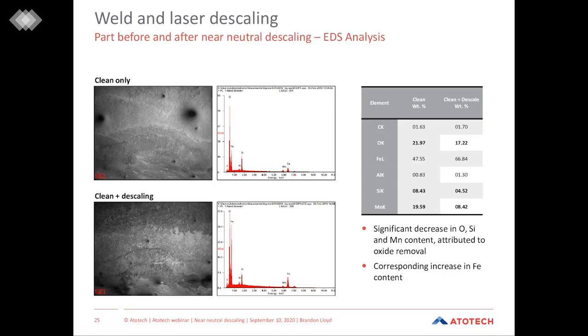And as we move to the right side, being the clean and descaling, we can see that the oxygen content for the clean and descaled part is reduced significantly. Also, we see the same with the silica and with the manganese. These significant decreases in these elements are directly attributed to the oxide removal. And what we can also see here is a corresponding increase in the amount of iron that is available from the EDS analysis.